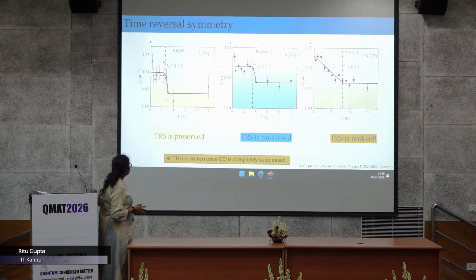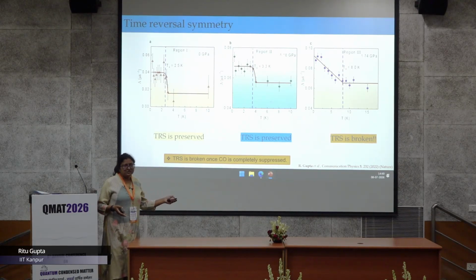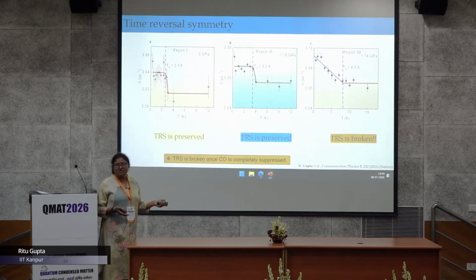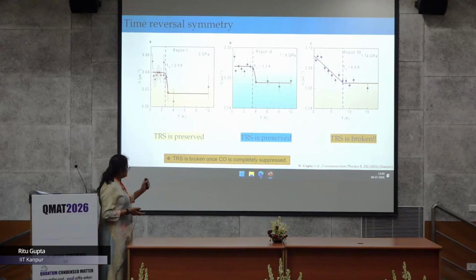So this might be because of the Meissner screening of the magnetic field, there is actually no time reversal symmetry breaking. But in region 3, where there is no charge order phase present, you can see a continuous change in the electronic relaxation rate, and there is reason to believe that time reversal symmetry is broken because there is no competing charge order phase here.